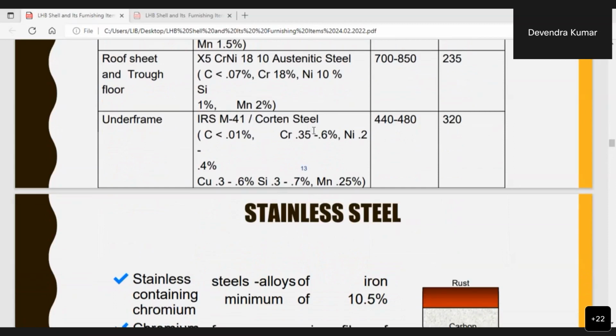In the underframe corten steel is used, whose composition is carbon less than 0.01%, chromium 0.35 to 0.6%, nickel 0.2 to 0.4%, copper 0.3 to 0.6%, silicon 0.3 to 0.7% and manganese 0.25%. Its ultimate strength is 440 to 480 Newton per mm square and yield strength is 320 Newton per mm square.